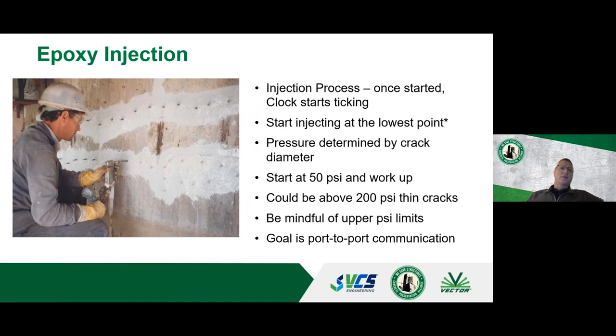Your goal is to start seeing, as you can see in this photo here, on the left-hand side, there's a bunch of ports that are in dark color. Those all have resin. All the ones to the right are still clear because the resin hasn't reached them. So typically you're injecting until you start having the resin come out to the next port. And then you're going to cap off that port, and maybe you keep injecting if you're getting good flow and kind of moving along.